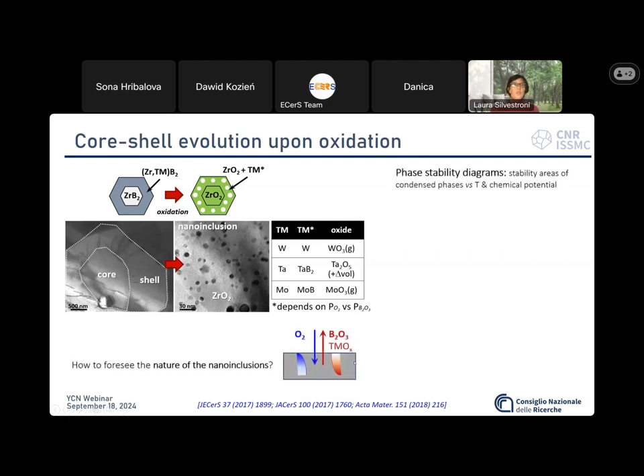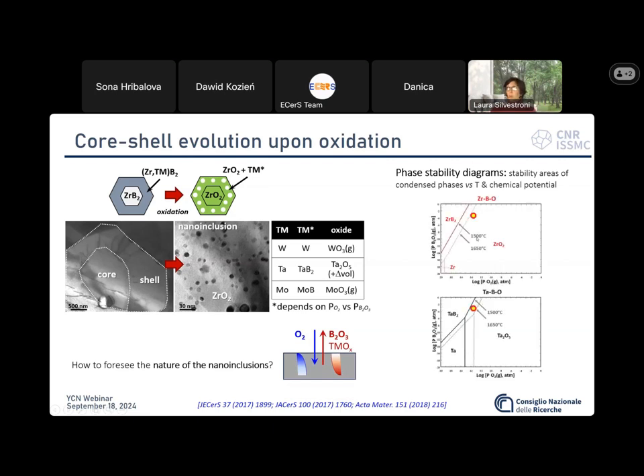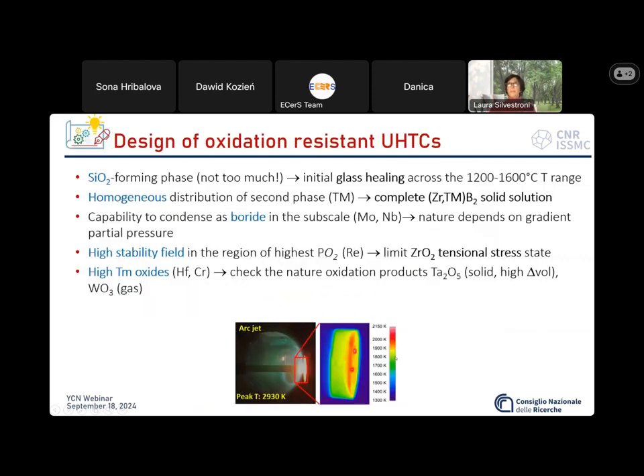One way to foresee what phase I will have in my oxidized shell is to use the phase stability diagrams, which look more or less like these, and they plot the stability areas of condensed phases versus temperature and the chemical potential. You can decide the temperature that you want to test, and you can see that at the same boron oxide and oxygen partial pressure, in one case we have zirconia, whereas in the other case we have tantalum diboride or tantala if we increase the temperature, and this fitted very well with our experimental finding.